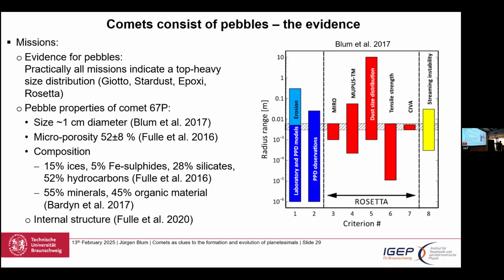Some years ago, we analyzed Rosetta data, and the typical size we found is this hatched region here, a radius of roughly 0.5 centimeter or 1 centimeter diameter. And that explains all the individual observations by different instruments, all the red bars here. It matches the streaming instability theory and also the observations of pebbles at the time. So there is lots of evidence that comets, when they come close to the sun and become dust active, eject most of their mass in pieces of dust that have the size of a pebble and also the porosity of a pebble.